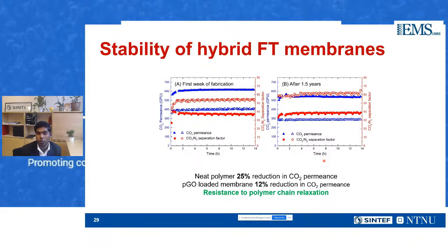But when we added this porous graphene oxide, these 2D materials helped in slowing down the chain relaxation. We only obtained up to a 12% reduction in CO2 permeance, while on the neat polymer membrane, the CO2 permeance was reduced by as much as 25%.